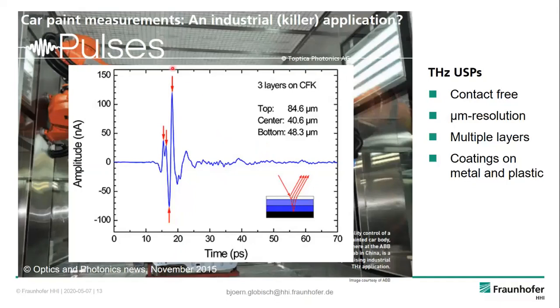And what you see here in the inset is a typical pulse trace of such a terahertz measurement, where you can see partial reflections. So these peaks here correspond to the interfaces of the different layers. And you can, in this case, nicely distinguish them by the eye. When the layers become thinner and thinner, it's getting more and more complicated. But this is the actual idea.